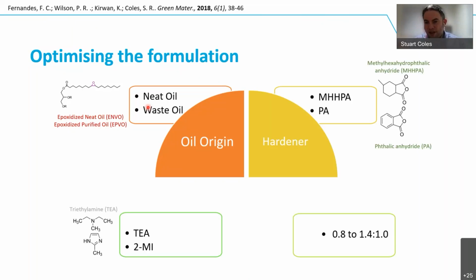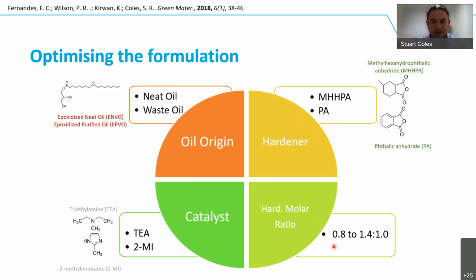Then we looked at the hardener, and we had two particular anhydrides. We had the phthalic anhydride and the methyl hexahydrophthalic anhydride as two different types of hardener. We varied the molar ratio of the hardener between 0.8 and 1.4, so maybe a slight excess of the oil or a slight excess of the hardener. And then as a catalyst to start this off, we tried two different catalysts as well, one being triethylamine and one being 2-methylimidazole. The idea here was really just to do a big broad range of experiments to try and find out what was going to be the best way to get the most bio-based content into a polymer without significantly dropping the properties.